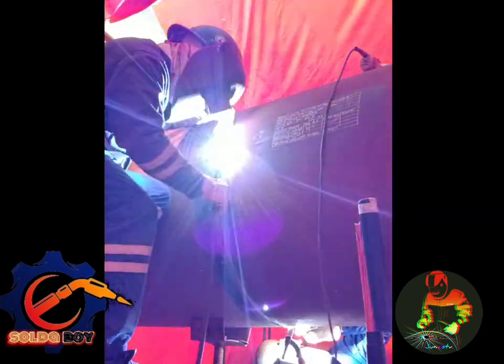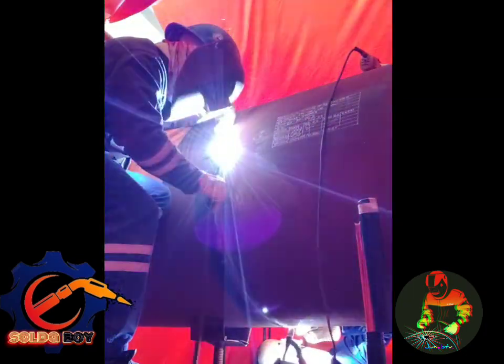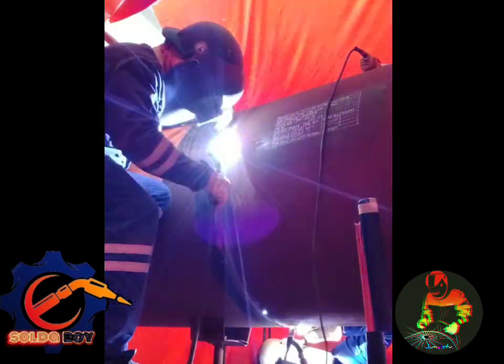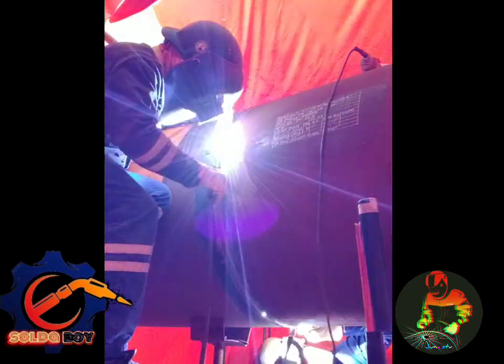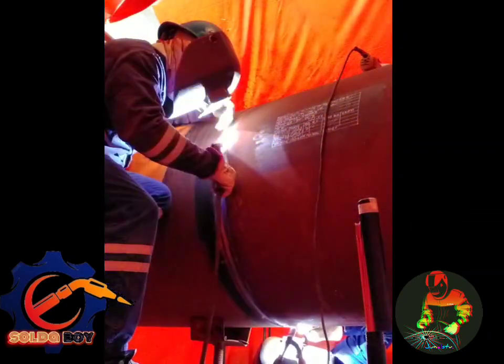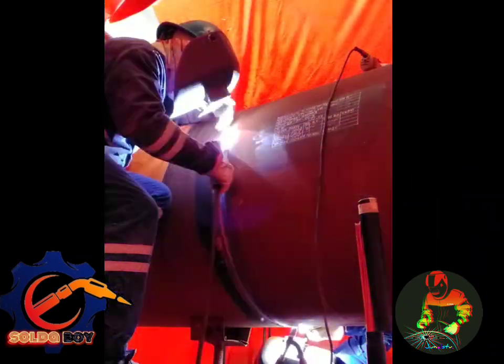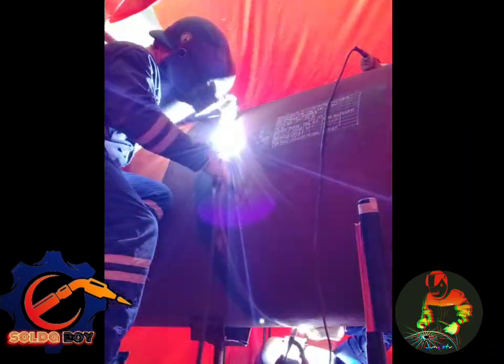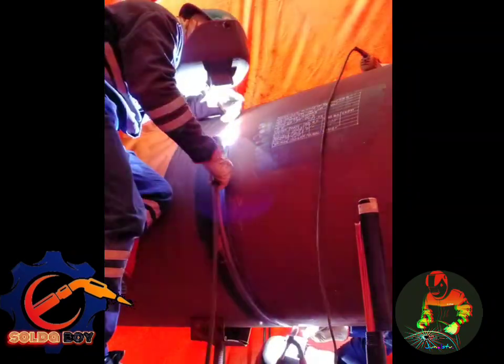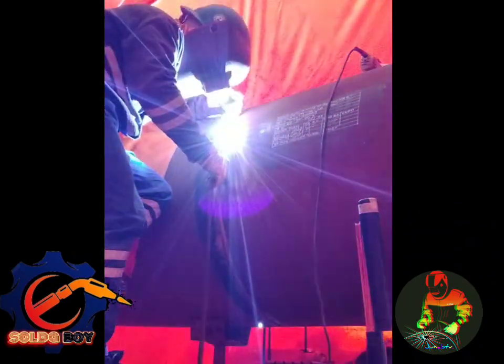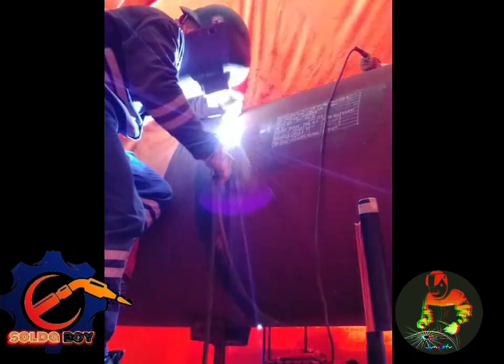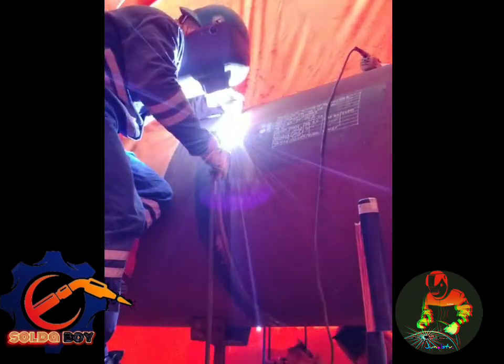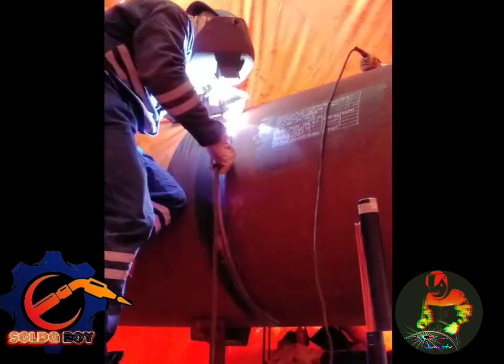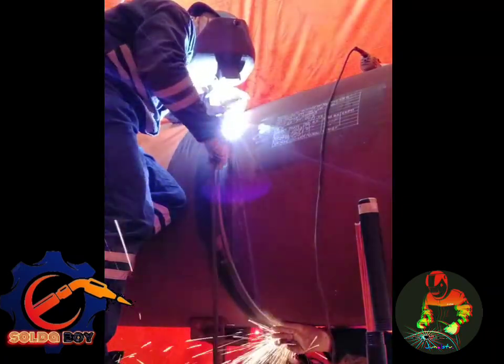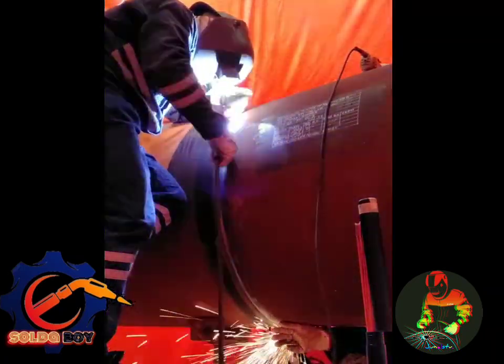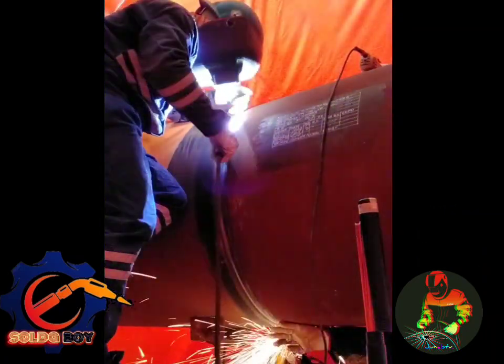With the hot pass, though, too much amperage is a danger because it will create a heat-affected zone in the root of the weld. Carrying too much heat into the root will cause the weld to become brittle and will be a breaking point when stress is applied. A hot pass should be rapid, and just enough metal should be deposited to dish the weld sides out, making it concave. Applying too much weld metal only creates another full pass, which may be run too hot.